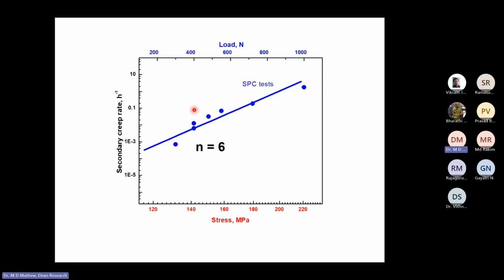If you plot the deflection rate as a function of stress, you find that on a log-log plot, you get this standard straight line, which is nothing but the expression of Norton's creep law with a slope of 6. So this is the data generated from the SPC curve. All the data at different stresses, the minimum creep rates or the minimum deflection rates, have been plotted as a function of stress, and you get a linear relationship, which means it obeys a Norton power law.